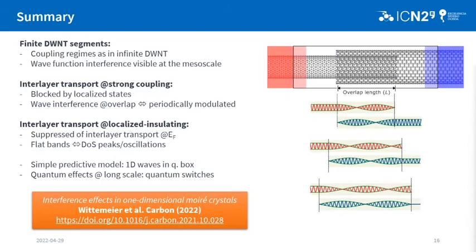I think for the individual tube, a simple tight-binding model is a reasonable approach, just like in graphene, where a first nearest neighbor tight-binding model already gives very reasonable results. But especially when we look at the interlayer interaction, that's where it's important to have a very accurate description, because there are tight-binding models that use a first or second nearest neighbor approximation in the interlayer interaction. Then, for example, they see strong dependence on the rotational alignment of the carbon nanotubes, whereas when we simulate that in DFT, we don't see that. I think that's because the interlayer interaction is discretized in such a way that if you rotate, you have more or fewer neighbors, depending on the exact position.